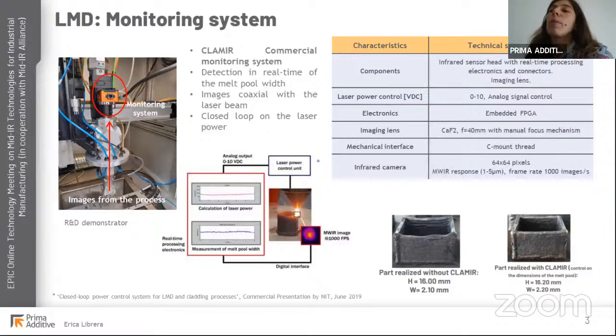This is the example reported in the slide in which an empty cube is deposited by a series of thin walls. What we can see is that without CLAMIR, the deposition is not flat, and we have a sort of overbuilding on the corners. The corners are a critical point because the process is changing direction and at the same time is decreasing the speed. These generate a sort of instability in the melt pool.